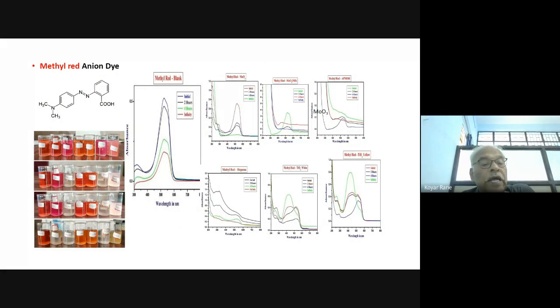Methyl red also can be degraded, or you can see that decolorization can be done in the presence of various catalysts, molybdenum oxide, titanium oxide, and all those things. Or in simple sunlight, it also degrades, not to that extent, but the degradation is higher in the presence of the catalyst in sunlight.